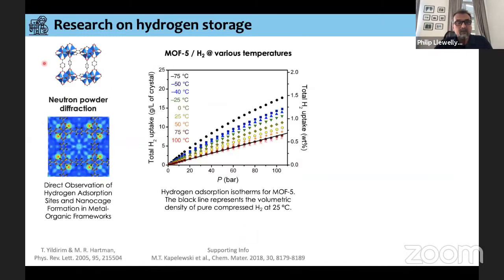So coming back to our MOF5 sample. Again, just to remind you of the structure up here. These are the sort of results that we will see for the adsorption of hydrogen at MOF5 at different temperatures. The temperatures are from around room temperature down to around minus 75 degrees Celsius, up to quite high pressure. What the authors have done here is compare the uptake on this MOF5 with respect to this straight line here. This line gives us an idea of the volumetric density of just the compressed gas at 25 degrees C. We can see that there is more hydrogen taken up in the material as we go down in temperature. It's logical. And we get an excess with respect to just the compressed gas.